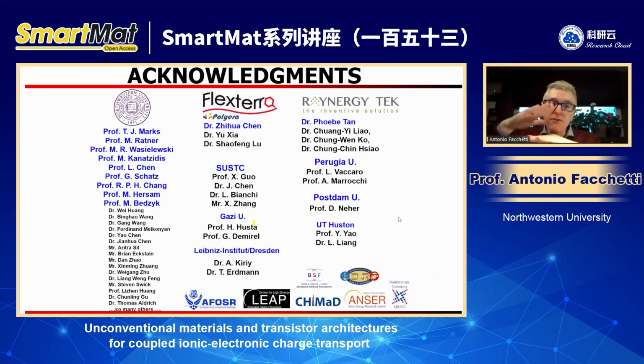I also showed you that the vertical OECT, where both electrodes are porous, so there is no ion penetration from the top or the bottom, the ions have to penetrate from the side, can be very efficient to promote electronic and ionic transport in OECT. And they can be very fast also, and we can make circuits based on them. And the last, we can take advantage of a P-type porous organic with an N-type dense inorganic to make electrolyte-gated circuits, again, which can be used to track physiological signals.